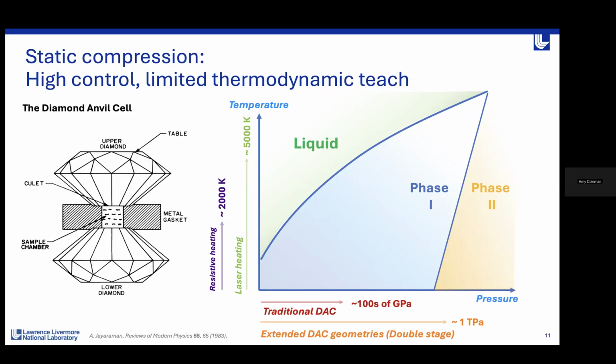And there have been reported pressures of up to a terapascal that have been accessed using these geometries. And we're certainly not confined to making measurements at room temperature conditions. In the context of this phase diagram, if we wanted to look at higher temperatures, we could employ techniques such as resistive heating or laser heating, which again, material dependent, but could get us up to temperatures of something like 5,000 Kelvin.